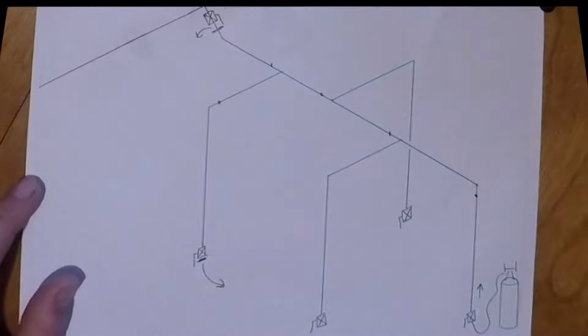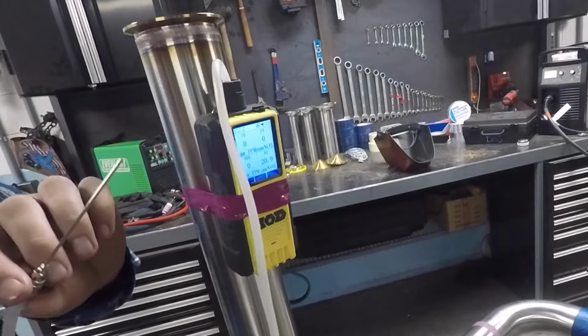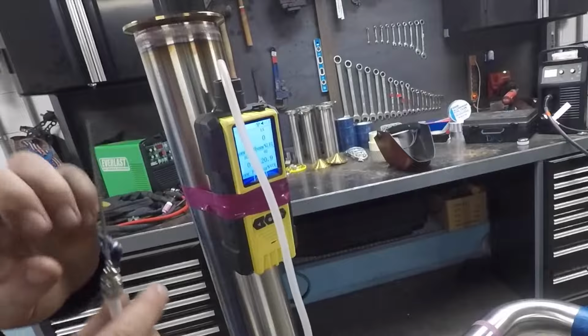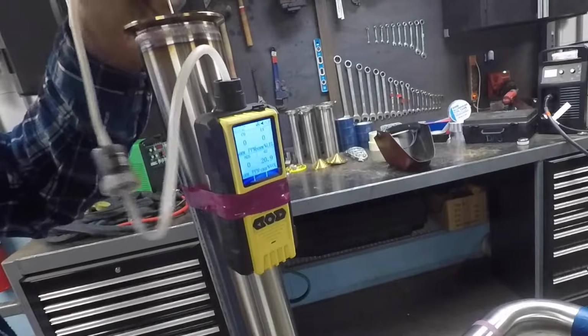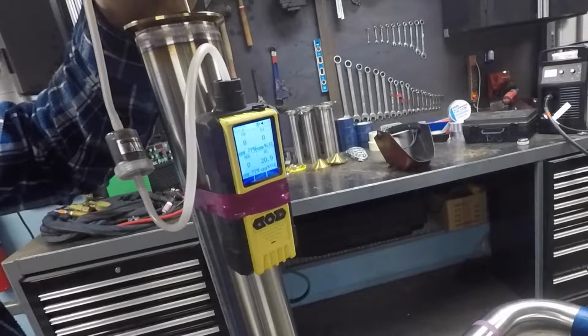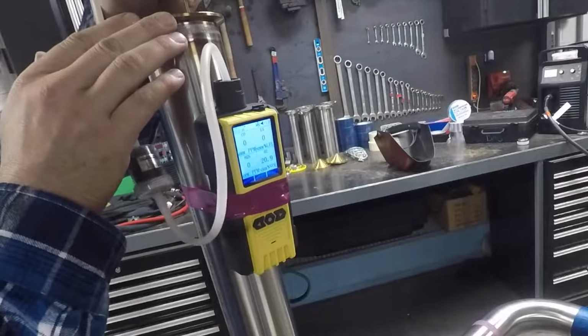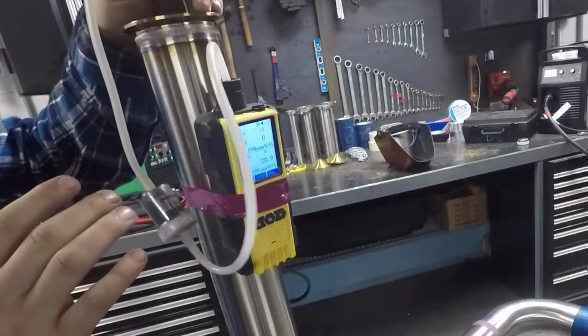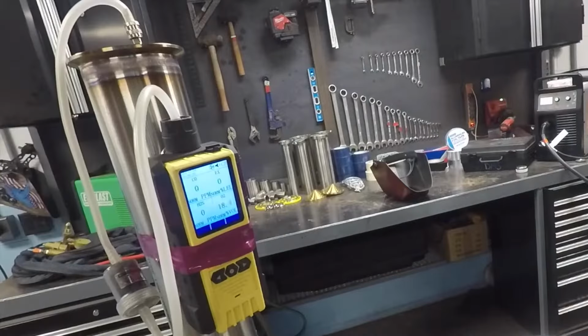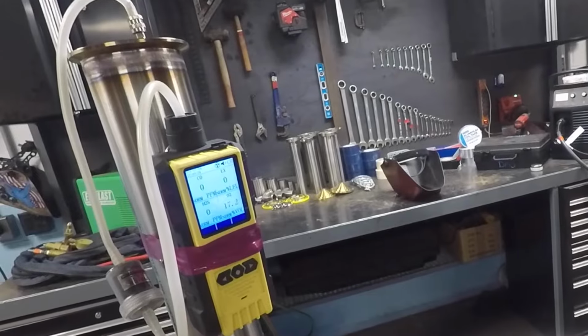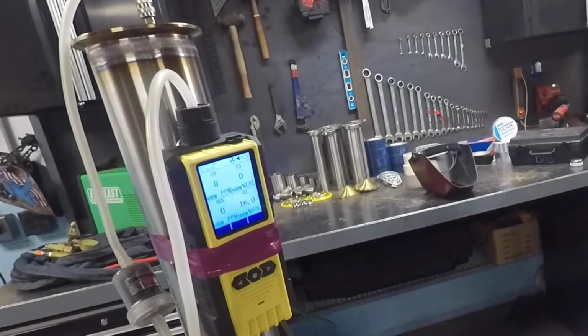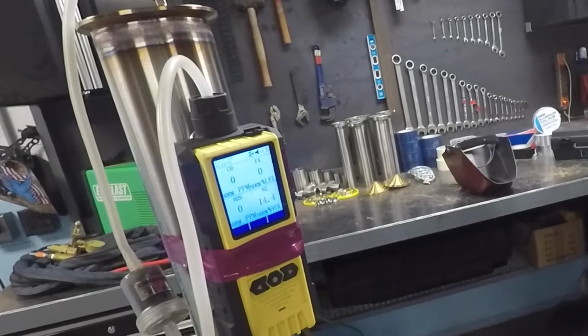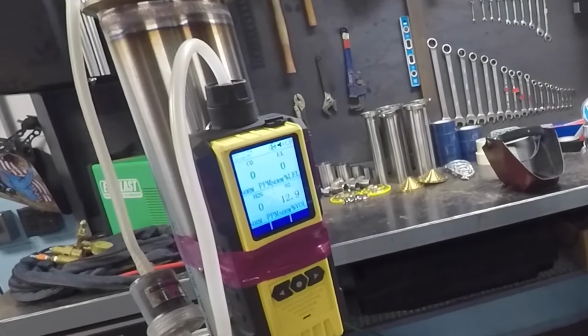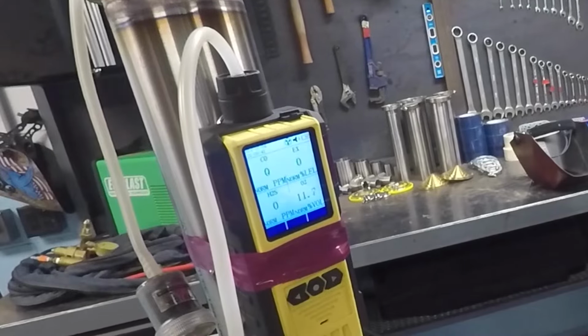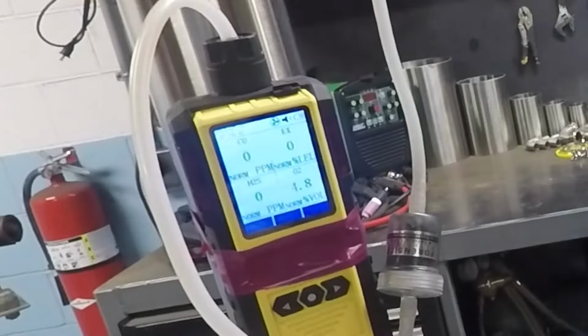One thing you want to watch out for on existing lines, in older plants especially, is traps in the piping or just sagging pipes where water or CIP chemicals can be trapped, not allowing your purge to flow past. So you always want to feel your purge, make sure it feels good and consistent, and also check it with a meter. This is my sniffer from Forensic Detectors. I use it for tank entry, but I can also turn off the alarms and install the probe and check the O2 levels inside of the pipe that I'm purging.